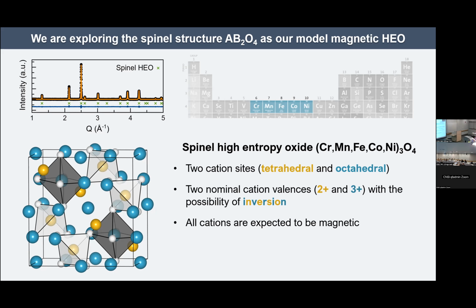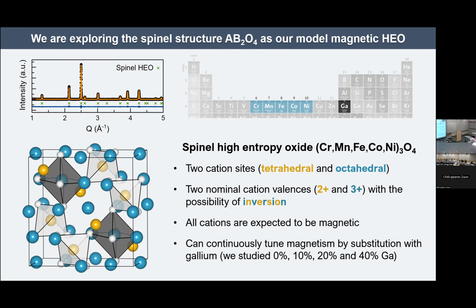And then because we wanted to study the interplay of disorder and magnetism, it was useful to have a tuning parameter for playing with that magnetism. And we've used the tuning parameter of dilution, where we are systematically replacing our magnetic cations with gallium 3+. And we've studied compositions of 0, 10, 20, and 40% gallium. So we're going to be able to percolate or dilute the magnetic order.